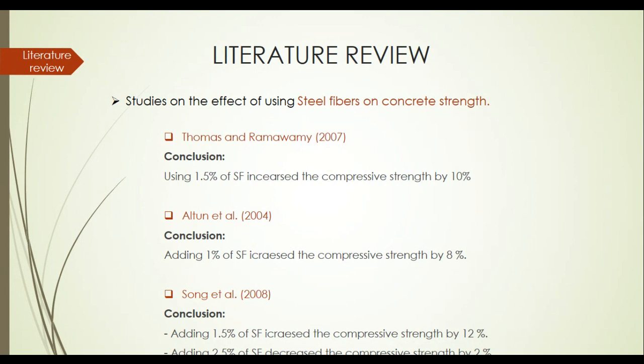On the other side, Song et al. 2008 found out that adding 1.5 of steel fiber increased the compressive strength by 12%, while if you increase the percentage to 2.5, the compressive strength will decrease instead of increasing. So there is an optimum value that needs to be added.